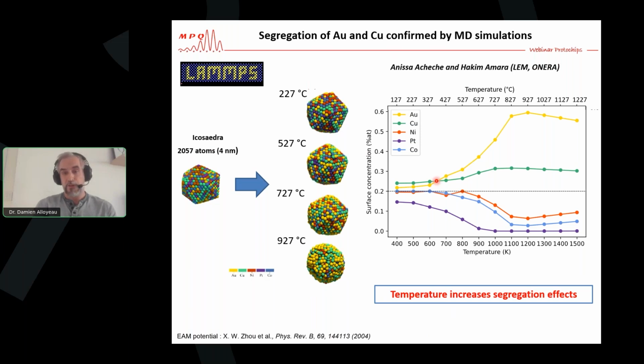And this confirms that the structural properties of those particles, the thermodynamic equilibrium of those nanostructures, is dominated by surface effects. We clearly observe that when you increase the temperature, you have a segregation of gold and copper to the surface, that you observe here, while the other metals go below the surface. So the temperature increases the segregation effect, and it means that the structural properties are dominated by the surface energy of each individual metal.